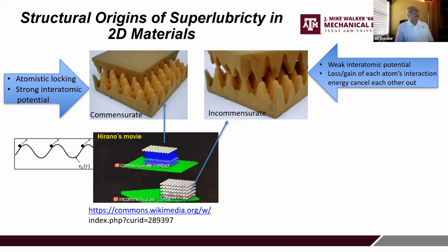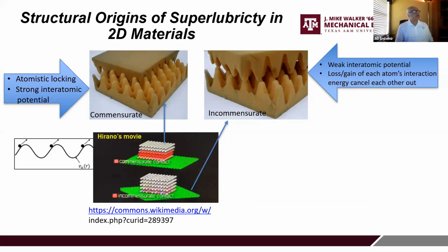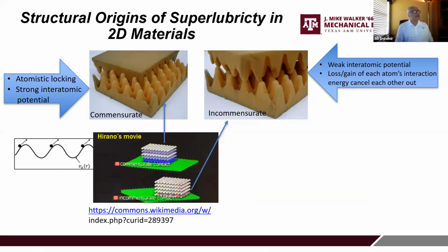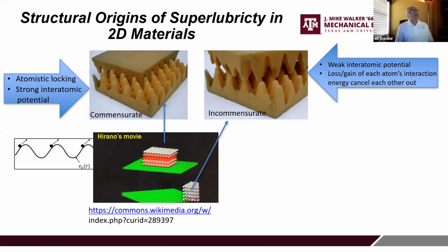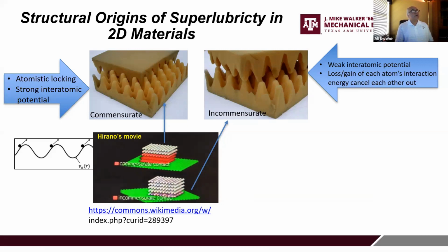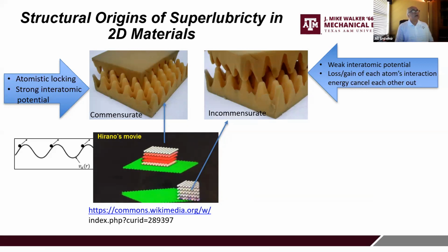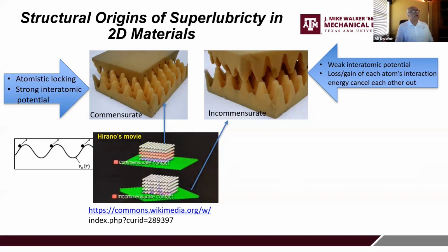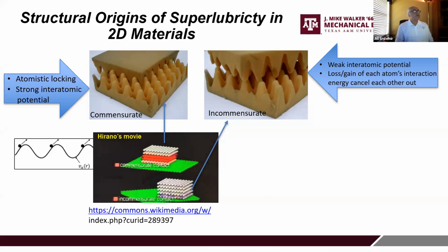And in the case of incommensurate state of contact, it turns out that if these surface atoms are twisted and brought out of that full registry, you have this state of incommensurability. This would actually produce or give rise to weak interatomic potential, and the energy loss and gain between these atoms will kind of cancel one another. In this particular case, you will actually have nearly zero friction.